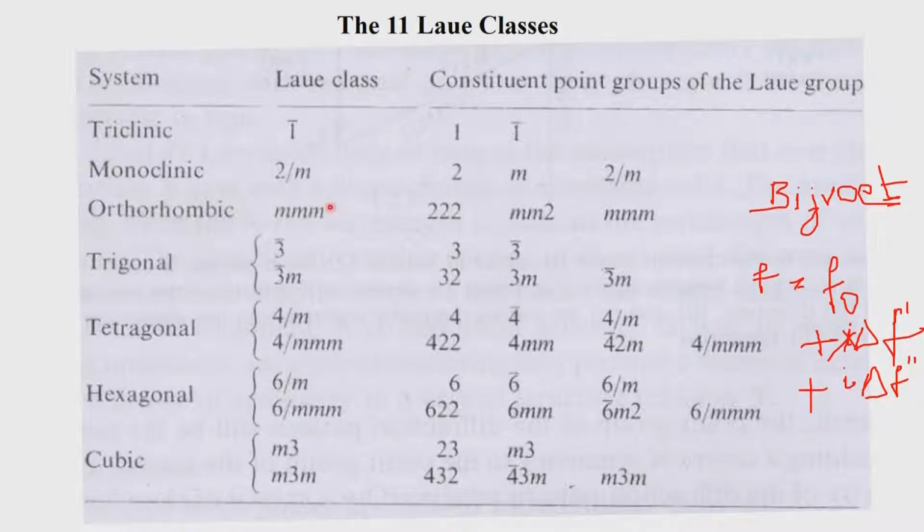The diffraction pattern, your HKL reflections which you get, will always be with respect to the center of symmetry. In addition, we have higher symmetry elements in monoclinic, orthorhombic, trigonal, etc., as we go higher and higher in symmetry. For example, because the b axis is unique and we have 2/m symmetry in the data, the HKL reflection will be equal to H bar K bar L bar, and also the H K bar L reflection will be equal to HKL.